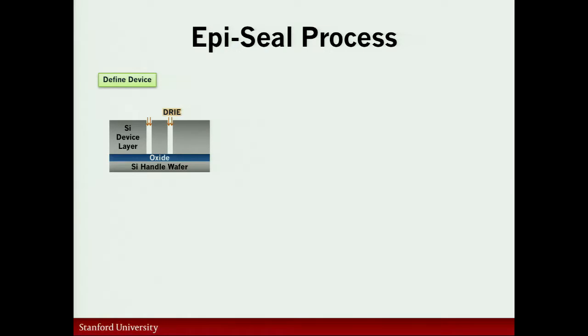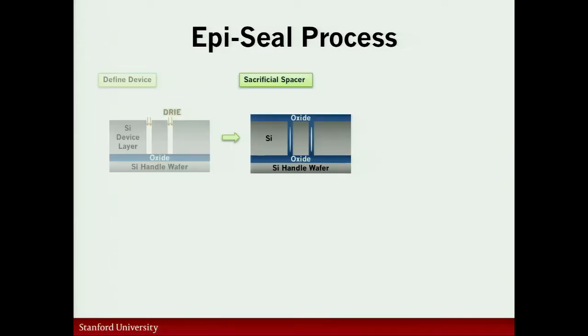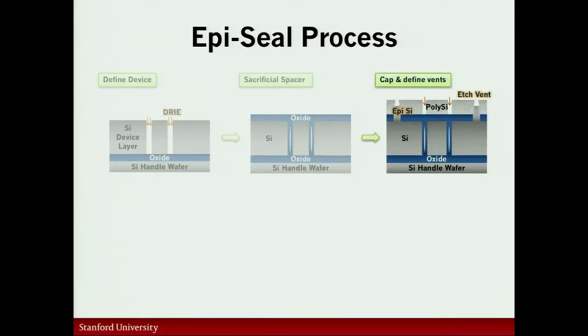We start off with a standard SOI wafer, so a device layer might be 30 or 40 microns thick. There's an oxide already there, and then a very thick handle wafer underneath that. We do plasma etching to form the boundaries of what will become the micromechanical element. We then fill in everything with oxide. This is a little unusual, but it helps us build the later steps of the encapsulation. So it fills the trenches and covers over the top surface. We then grow the first thin portion of what becomes the package. This might be 5 to 10 microns of polysilicon using this Epi-Poly process. We do some patterning of this to create access points for the electrical contacts. But otherwise, it's just polysilicon.